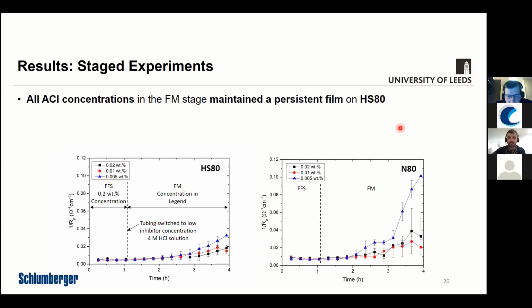And what you can see for the HS80 is that the inhibition efficiency still remains fairly high during that period, and we don't see a dramatic increase in corrosion rate. The film formed on the surface remains persistent. Towards the end of the test, we start seeing some change, but no dramatic increases in corrosion rate. On the N80, however, and I should point out that's for these inhibitor concentrations which I just showed you, the 0.005 weight percent, blue line here, is maintaining some pretty high levels of efficiency. And when you compare that to the slide I just showed you, where essentially there's no inhibition, it shows you just how critical the film forming stage is.